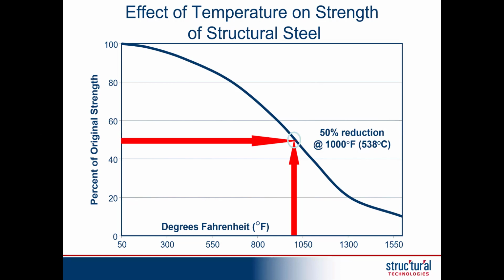Now, I talked about the temperature being important with structural steel members, and we're really looking at 1,000 degrees Fahrenheit as the go, no-go for the fire rating. And that's where there's a 50% reduction in strength, and we see that as important because that's when that structural steel member, and for testing it's a W10 by 49 that they use to standard test these products. But we're looking at a 50% reduction in strength, and that's what is believed in the industry as enough to cause buckling and or collapse. So that is how we get our fire rating, is the time to where that internal member reaches 1,000 degrees Fahrenheit, and how we do that in the testing procedures by thermocoupling the actual structural member itself.